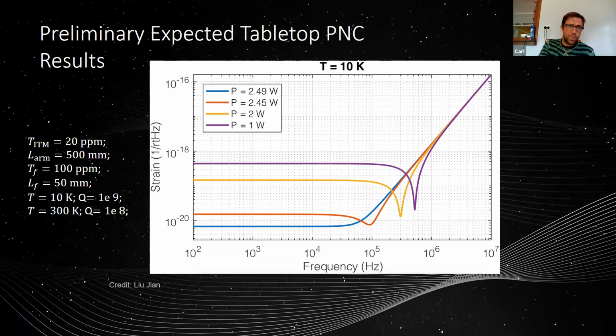Here we see preliminary expected results for the tabletop experiment at 10 Kelvin with fairly high power in the cavity. This is probably beyond the damage threshold of the photonic crystal. We should be able to measure a significant change in the system. This is all referred to some arbitrary strain.